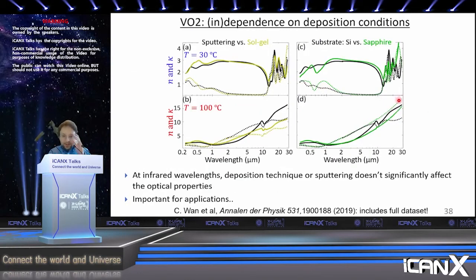One thing that we found that was interesting is that we spent some time figuring out the dependence of the complex refractive index on the deposition conditions and on the substrates. If you look in the literature again, you find that even in the same wavelength ranges, the VO2 complex refractive index differs dramatically from sample to sample and group to group. This is very strange, and also very inconvenient, because it means if you ever do make VO2 devices yourself, you have to characterize your own materials from scratch.